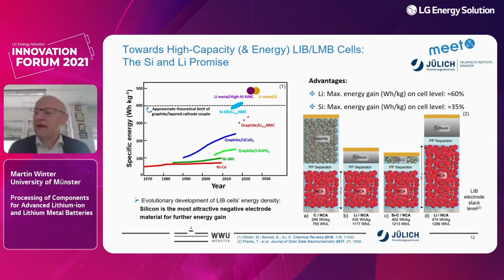This slide does not tell you anything about safety and cycle life. It only tells you something about specific energy. And you get this because in a given volume, you can then use the space for anode and cathode more properly if you use a thin lithium metal anode or even a thinner silicon carbon anode, indicating to you that lithium metal is not a high energy density, but a high specific energy material